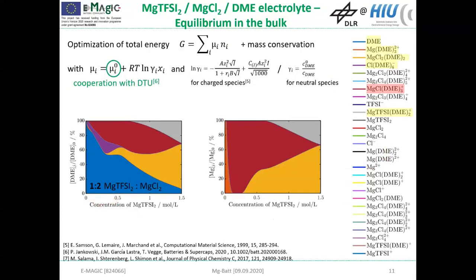And here on the left, you can see the relative amount of DME which can be found in which species, and here on the right, you can see the same for magnesium. As this color coding is quite complex, I highlighted the relevant species. We see that at very small electrolyte concentrations, the magnesium salts are fully dissociated. But when we get to more practical concentrations, the solvated magnesium chloride plus becomes the dominating species in the electrolyte. When the electrolyte concentration further increases, the neutral solvated magnesium chloride and the solvated magnesium ion pair become thermodynamically favorable. And at even higher concentrations, we see the formation of bigger clusters, especially of this magnesium 3 chloride 4 cluster.